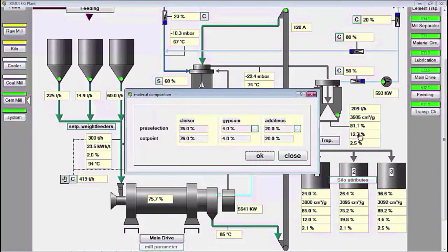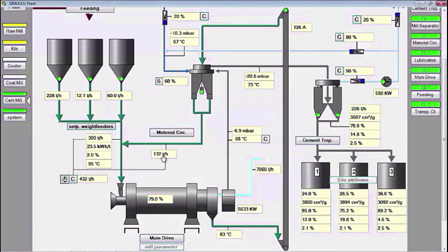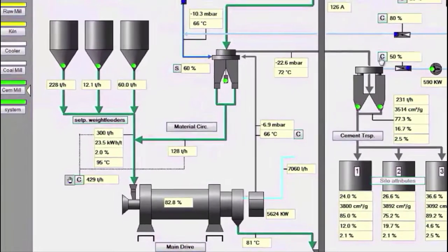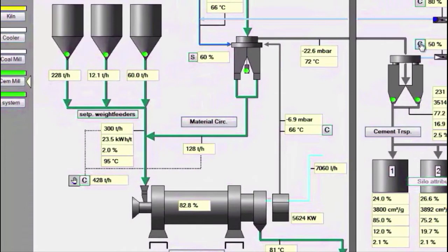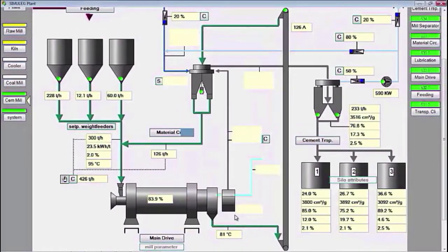Then this additive material has started to rise, and the clinker ratio has started to fall below 80%. This circulating material has started at 132 tons, but Blaine is still 3,500, so we try to increase the draft at the mill outlet. This is 6.9 millibars. We increase the mill ID fan damper opening from 50% to 60%, while we observe what the effect is on the milling process inside the ball mill.